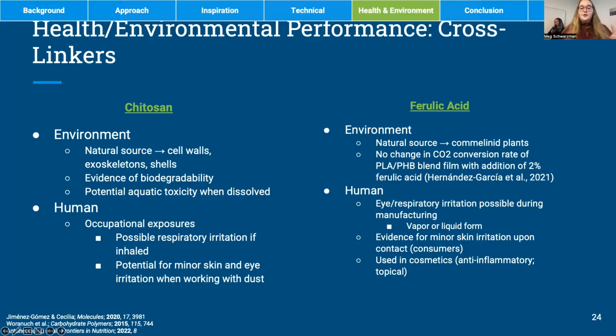Ferulic acid, on the other hand, we were able to find some good metrics on biodegradation, similar to the silicon nanoparticles that I mentioned earlier. This had no change when applied to a blend film of PLA and PHB. So the carbon conversion rate remained the same, and it was completely biodegradable, but it didn't impact the rate at which that happened.